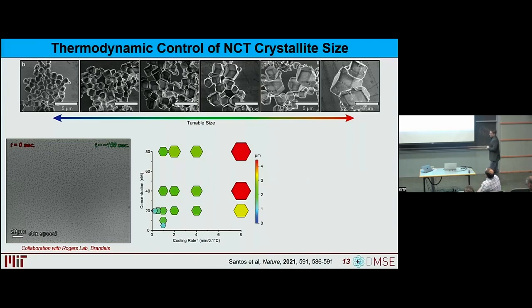particular systems. Those of you that are paying attention or that paid attention in your MatSci 101 class maybe have already seen one of the weird things about crystal nucleation and growth with these NCTs, which is I noted that as we increase the concentration, the crystals get bigger. MatSci 101 would tell you that in classical nucleation theory, if you increase your concentration, you should have more nucleation sites and therefore smaller crystals. So why is it that we see a larger crystallite when we actually increase the concentration?